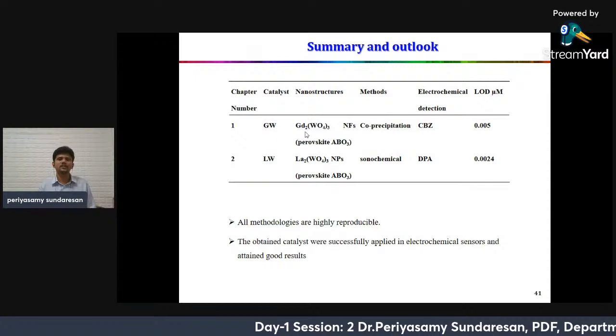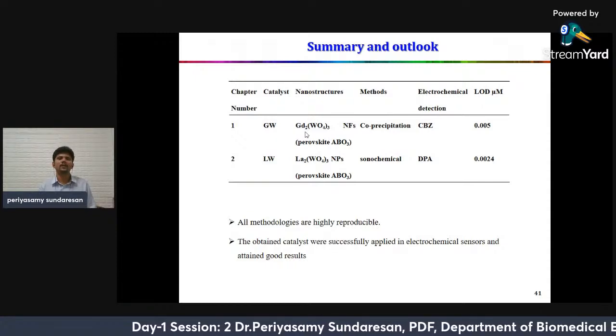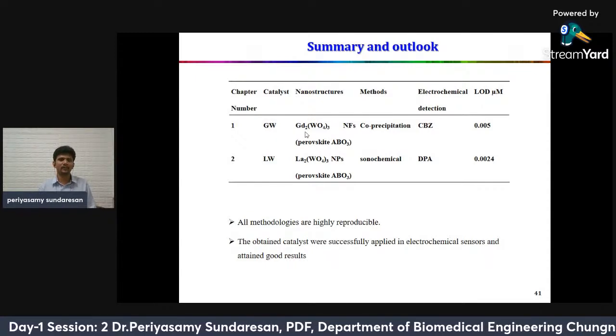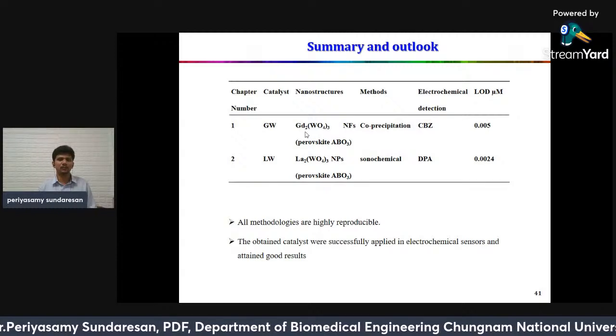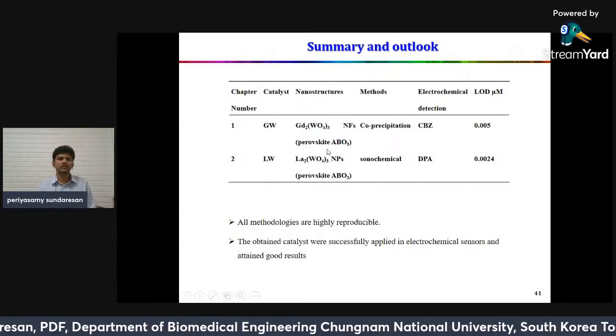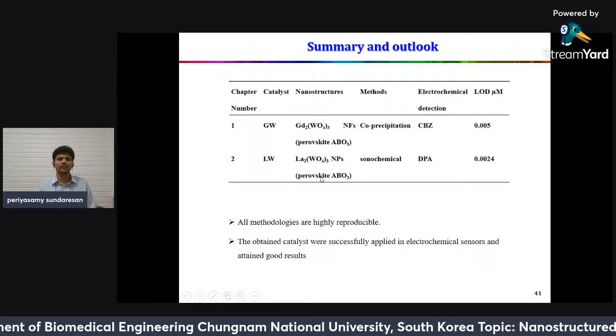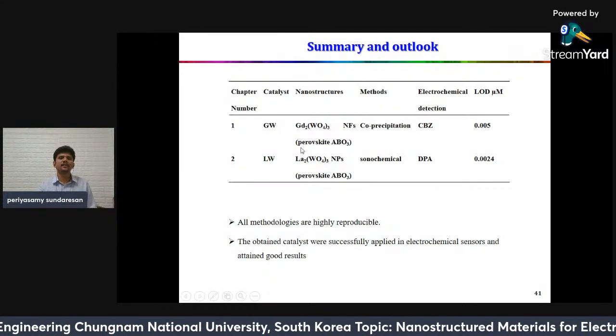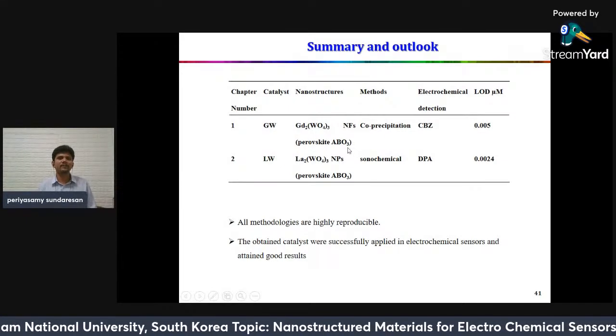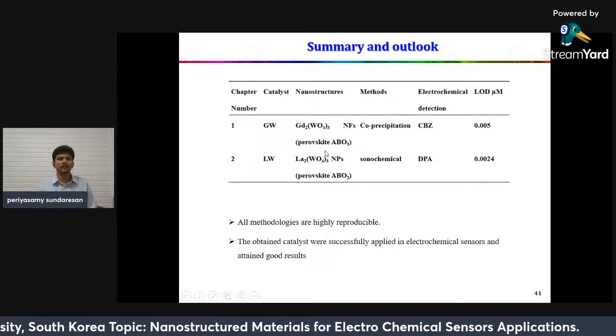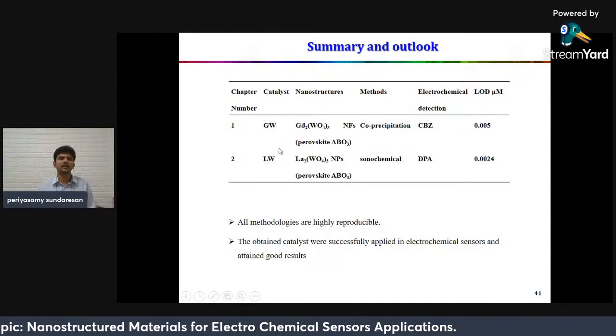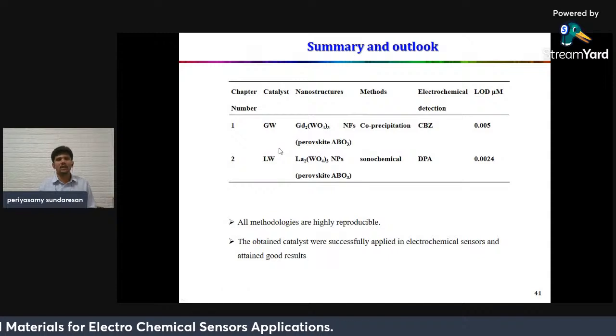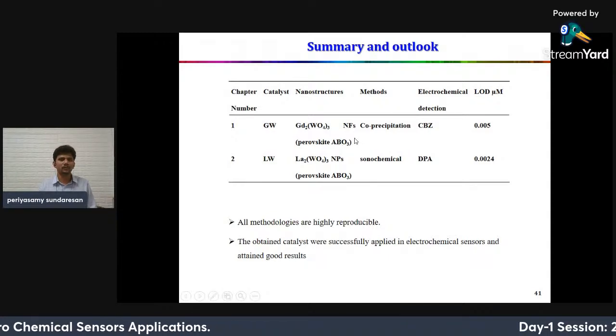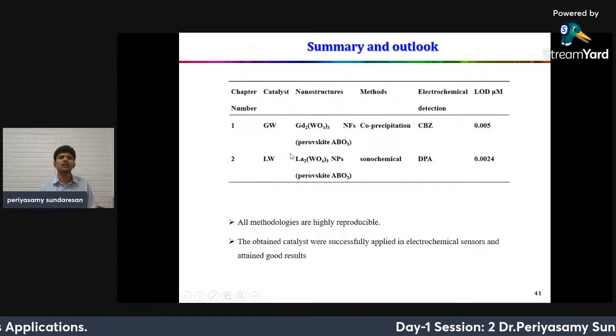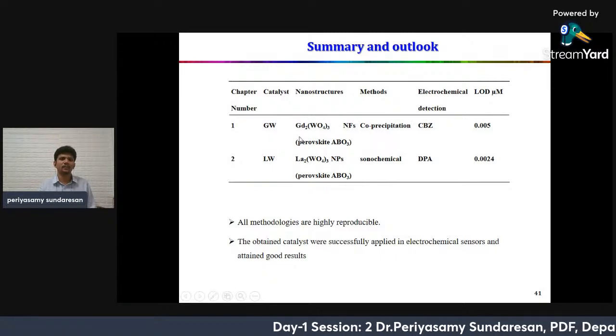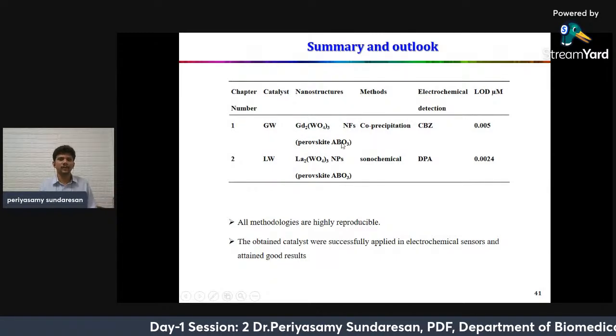And this ABO3 structure has good active properties for electrochemical sensors, similar to the carbon group. That's why I am studying the ABO3 type perovskite structure. The basic principle of perovskite formation is the oxidation state, and the oxygen and cationic vacancy are very important for perovskite structure formation. That's why I selected the rare earth element group for the material preparation.